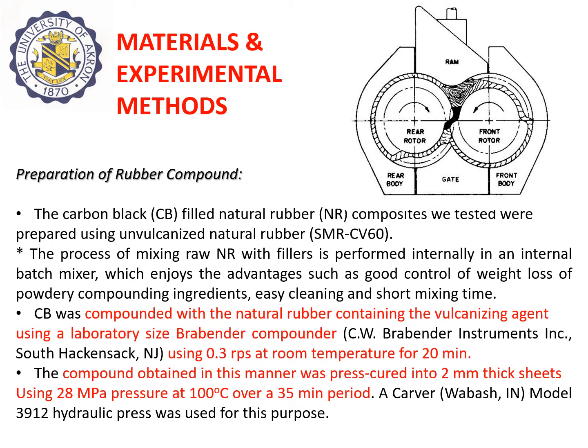We prepared the rubber compound, which was filled with carbon black in natural rubber, in internal mixers by starting with an unvulcanized form of the natural rubber, which had the commercial designation SMR-CV60. Such internal mixers are quite practical. They have good control of weight loss and short mixing time.